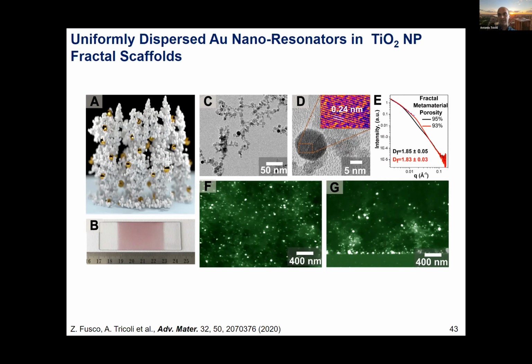Also another challenge is that when you start doing this coalescence, for certain material you may change the surface. So we have to make sure that we can also have the same type of surface as the one done with a lower coalescence temperature. However, I think it's possible to do it for some few materials, and it would be a very good thing to study. One way we have done this more or less, it was by increasing here the time.